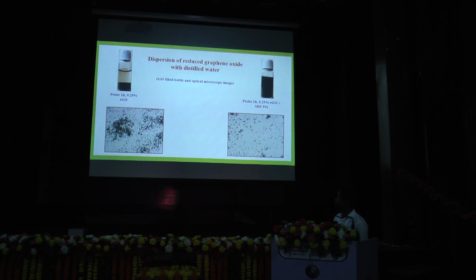Because after dispersion, after 1 to 2 hours, it starts to settle. So we use sodium dodecyl sulfate to reduce the surface tension, and the second image is properly dispersed with the distilled water.